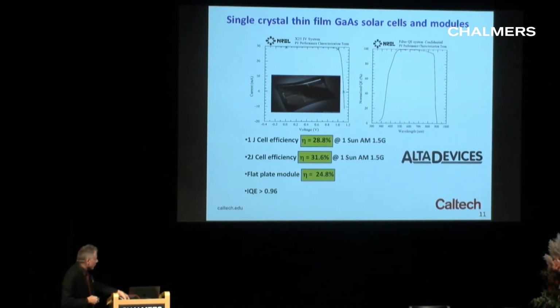And as a result, we can make thin film solar cells. At Alta Devices, we developed a technique for peeling off thin films, like you peel a Post-it note off a pad of Post-its or a piece of paper off a pad. So we can use a relatively expensive substrate, peel off a layer, grow another layer, peel it off, and use that substrate hundreds of times.